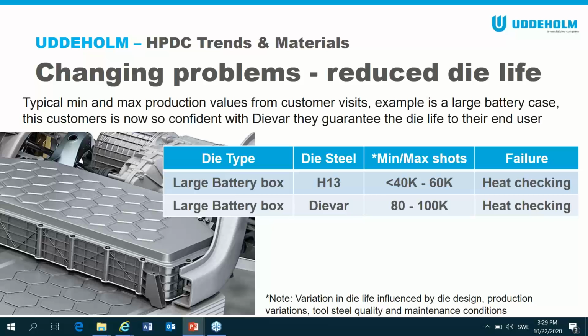On all their presses from 3,000 tons and over, they actually insist on Dievar for everything. Everything's Dievar, because they know it's so much better at crack resistance than an H13. And what they do there, this is a battery for a bus. The part itself is just over a meter long, about half a meter wide, about let's say 10 inches deep. And this box itself gets about 80 to 100,000 shots in Dievar.